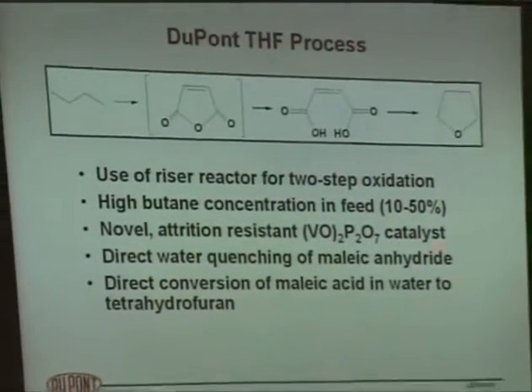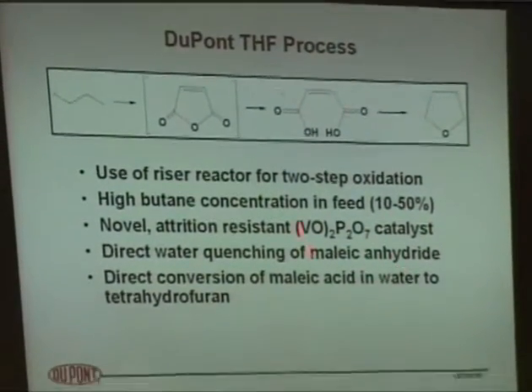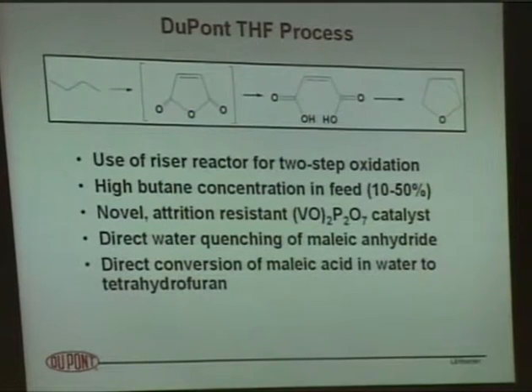We feed as high as 50% butane in that process. There's a novel vanadium pyrophosphate catalyst I'll tell you a little bit about. We do the water quench and then eventually make tetrahydrofuran, which goes into spandex and lycra fibers, some of those wonderful fibers that we sell.